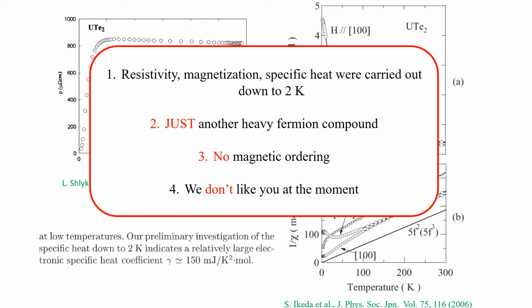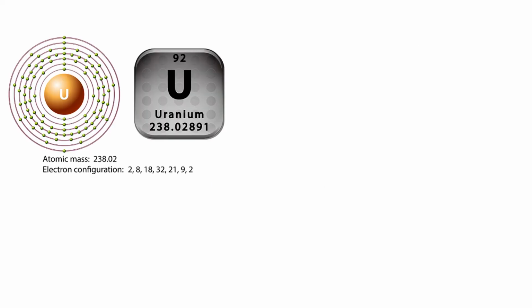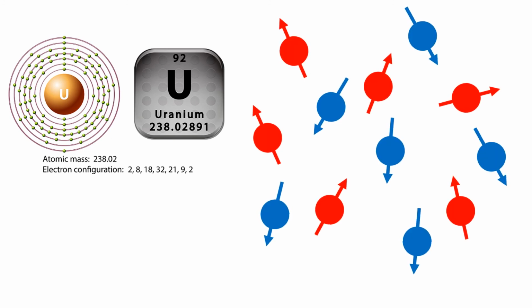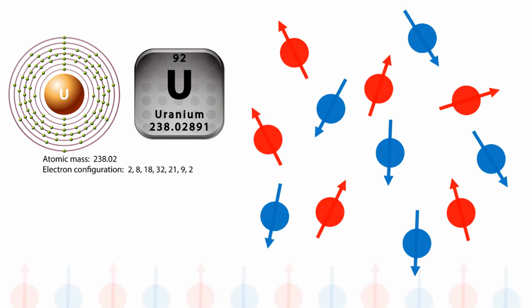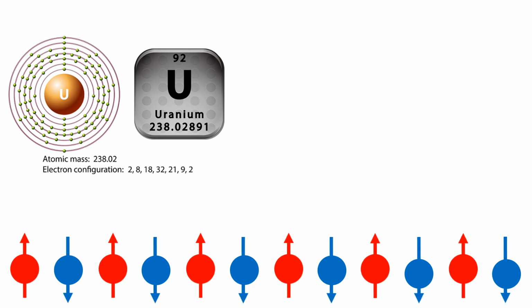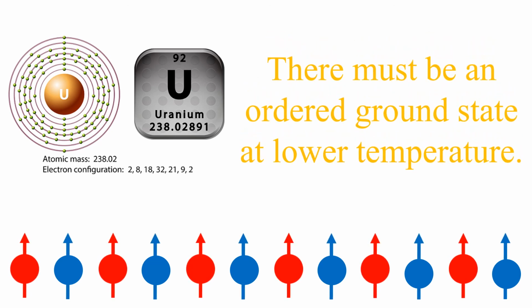So it was a boring material, but to me, it's very interesting to see how boring this material is. Keep in mind, this material contains uranium. For those who are not familiar with the periodic table, uranium is at the bottom of the table, where everything contains unpaired f electrons. At high temperatures, f electrons are randomly oriented, but at low temperatures, the system would like to release entropy by getting into an ordered state, either an antiferromagnetic order or ferromagnetic order. I really think there must be a magnetic order at lower temperatures.